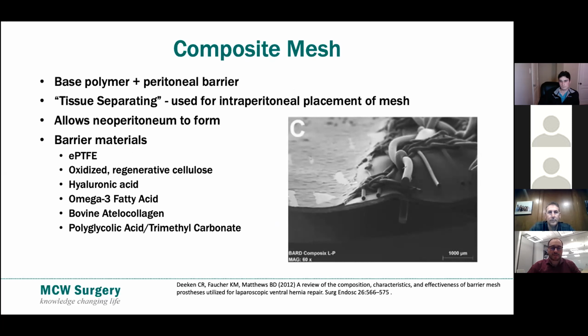So most of the materials utilized do resorb over time, and the required timeline for a mesothelium to form is between 5 and 7 days. So all of those last longer than that timeline. However, PTFE is also utilized. That's a permanent construct. There's regenerative cellulose, a hyaluronic acid, fatty acid, collagen construct, and then polyglycolic acid and trimethylene carbonate is actually a material that's being utilized in the resorbable synthetic constructs as well. So it's actually being used as a base polymer too, which we'll talk about in later lectures.